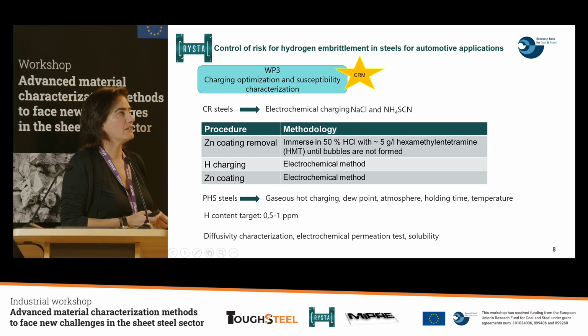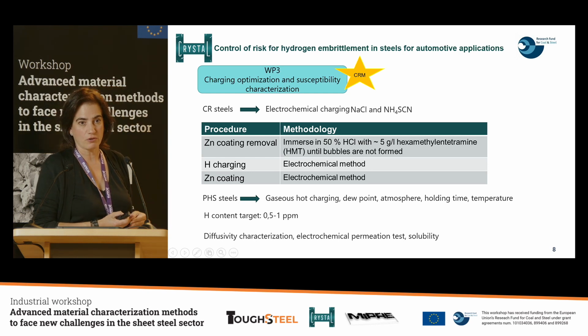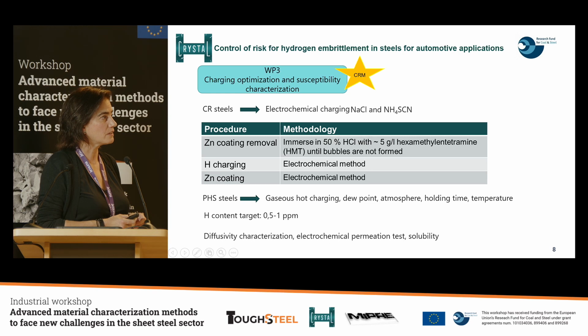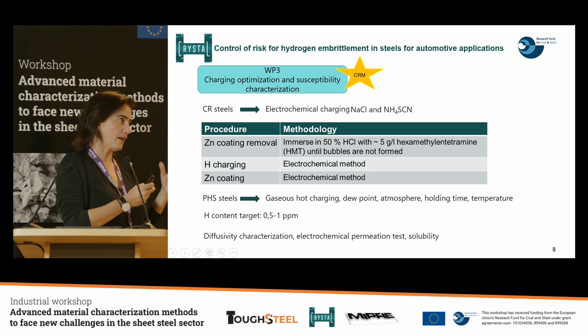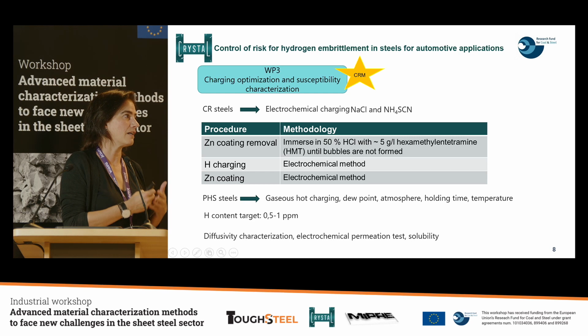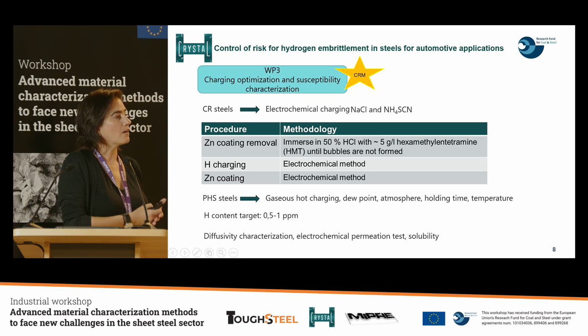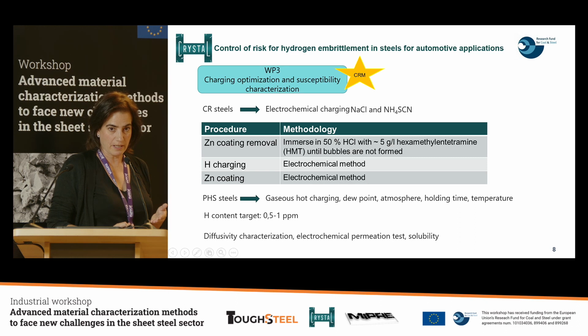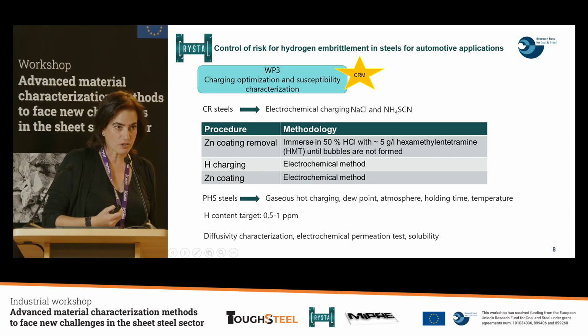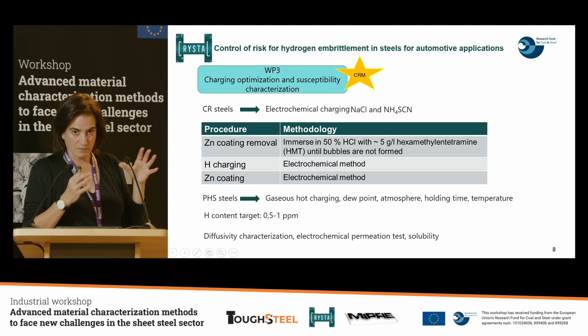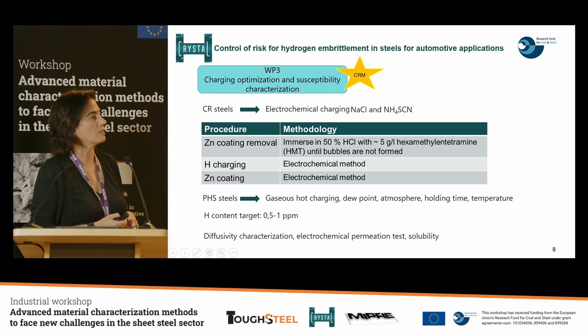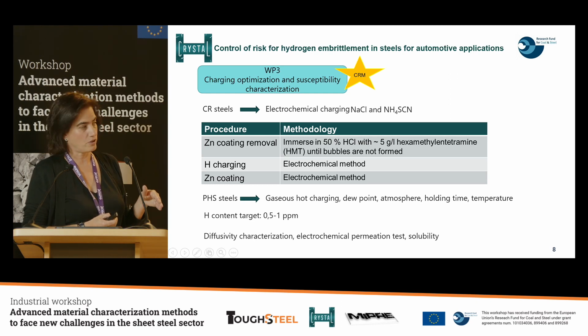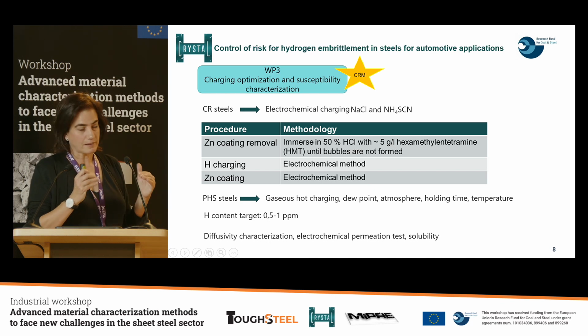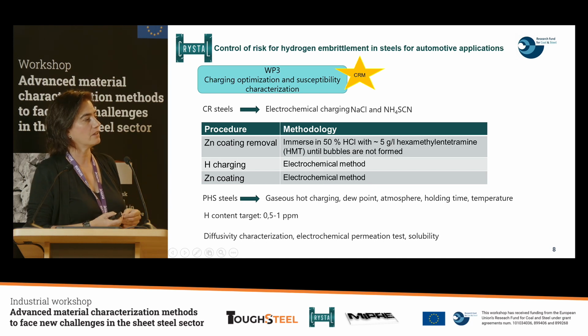So here is work package 3, where we optimize the charging methodology for these 2 types of steels. In the case of cold-rolled steels, we electrocharge using a mixture of sodium chloride and ammonium thiocyanate. And we have to remove the zinc coat, then charge with hydrogen, and then apply a zinc coat again to keep the hydrogen in the steel, in the microstructure. So we have to optimize these 3 methodologies: how to remove the zinc, how to charge the samples or the cold-rolled steels, and then to zinc coat again to obtain a thin and dense zinc coating.